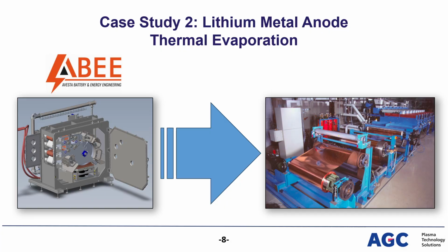A second collaboration is in the field of lithium metal anode production, where thermal evaporation is used as an alternative to extrusion and lamination of lithium film. Lamination of thin lithium metal becomes challenging below 20 micrometers, while thin film technology allows to tune much thinner coatings, applying the strictly necessary lithium content on the copper foil in a reliable and reproducible manner.